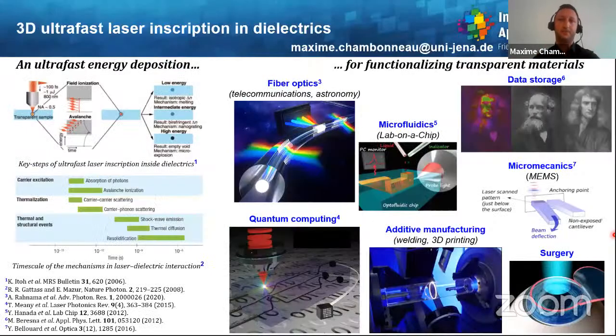So, as you may know, ultrafast lasers represent an extraordinary tool for functionalizing dielectric materials, especially glasses, but also polymers. And the reason is contained here on the left, because at those ultra short timescales, it is possible to first deliver energy to the electron subsystem, and then this energy will be released well after to the lattice. And this allows you to have a clear separation between the causes, which are the energy deposition, from the consequences, which are the material response.